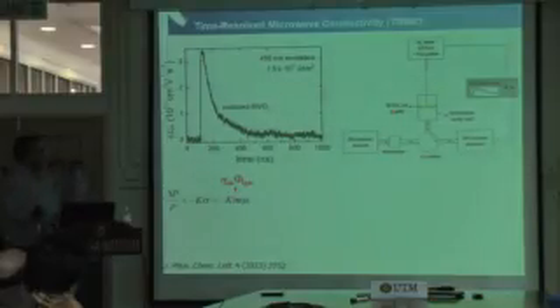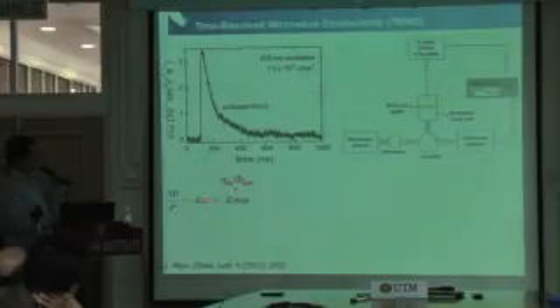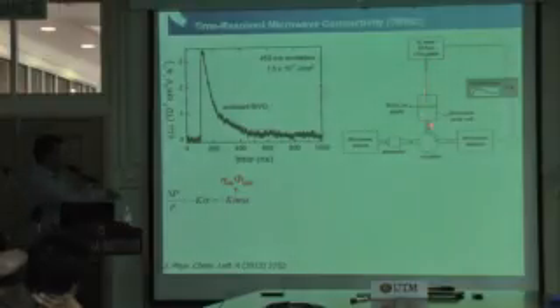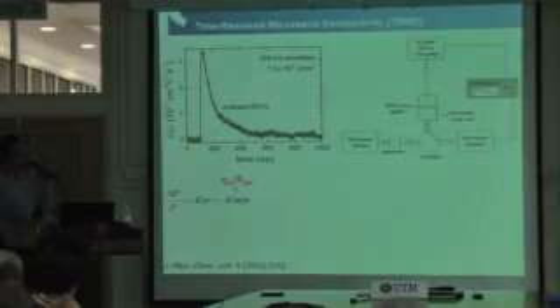And if you excite it, you create a lot of mobile carriers. From the change of the microwave power that you detect as you excite, you can then correlate this change of microwave power to the change in the conductivity. And the change of the photoconductivity, as we know, conductivity is a product of the carrier concentration and mobility. And we know the carrier concentration because we know the amount of laser pulse that we illuminate. Then we can actually calculate the mobility. So this is a fast and contactless method in order to measure the bulk properties of our material. But the lifetime has to be longer than 1 nanosecond. If you have a lifetime shorter than 1 nanosecond, this is not sensitive because it's limited by the experimental apparatus.